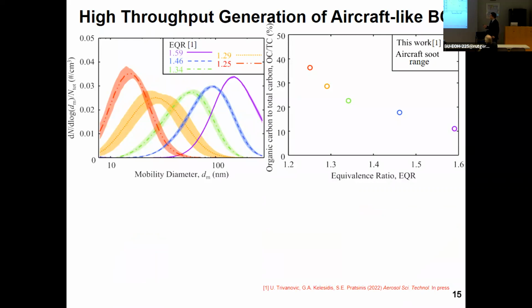So by changing the equivalence ratio over here in the flame, we're able to produce black carbon nanoparticles, the red, the orange, the green lines that you see over here, that have a similar size distribution to those emitted from actual aircraft engines. And furthermore, over here, due to the light, it's not shown that well, but these nanoparticles contain the same amount of organics as those obtained from actual aircraft engines. So this shows that we can use such a reactor to produce nanoparticles in our laboratory that are very similar to what is coming out from an aircraft engine.